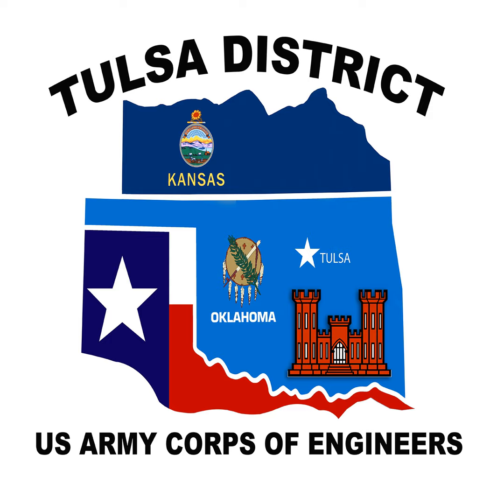But then we've tested some full-size beams that were 45, 50 years old, and we saw that, with pretty extensive damage, that actually happens earlier than what it does for an undamaged beam. So somewhere in between, the 7 years we've tested and the 45, 50 years for out in the field, that original increase in strength turns into a net decrease.